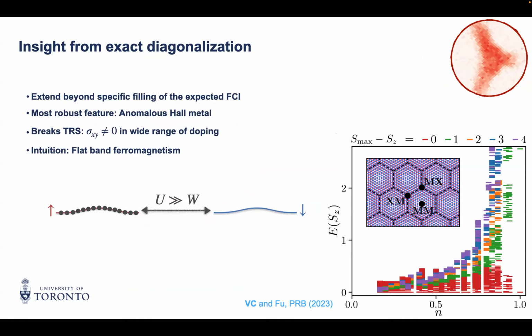So if you do a calculation on a system that tries to describe twisted MoTe2, what you see is indeed a large portion of the phase diagram is dominated by a metal. So many states here, it's a continuum. That is ferromagnetic, so the full spin polarization are the red lines here. So what you see is a ferromagnetic metal. At nu equal to 1, it's no longer a metal. You've completely filled the band, and so you have the quantized sigma xy insulator, the Chern insulator here, right?